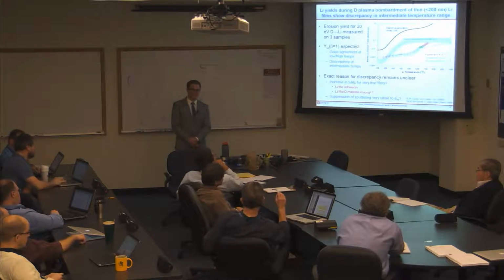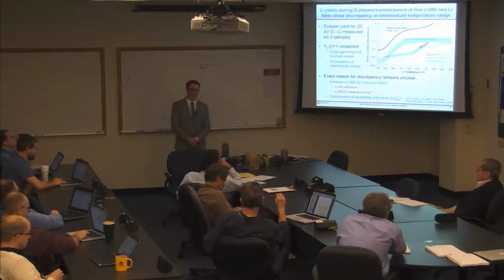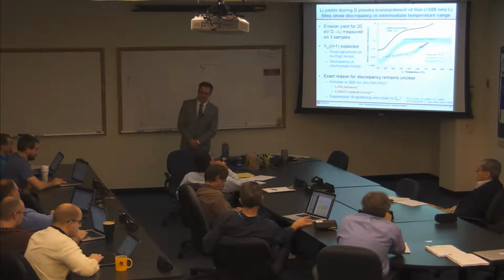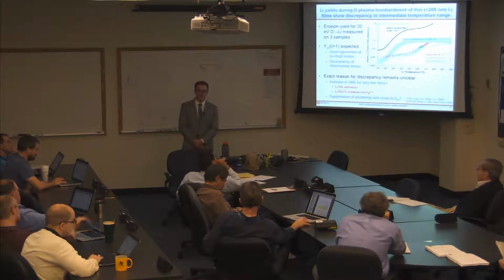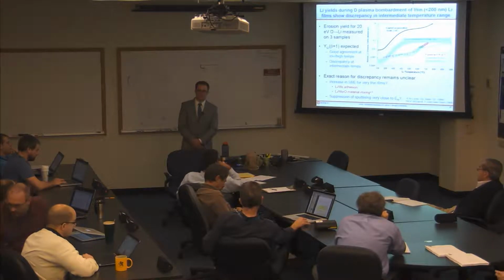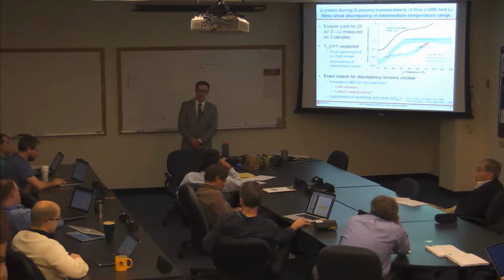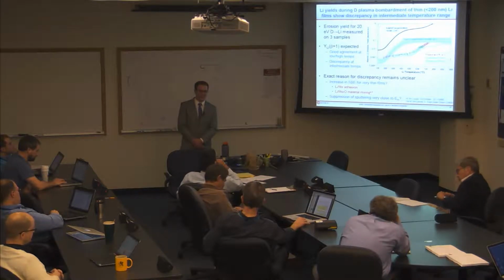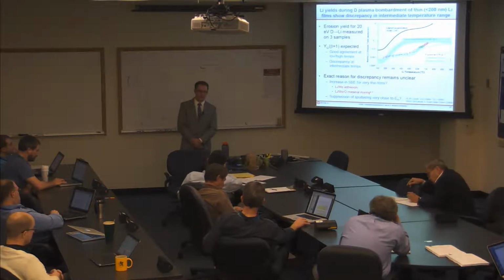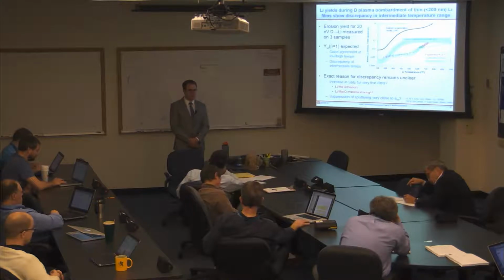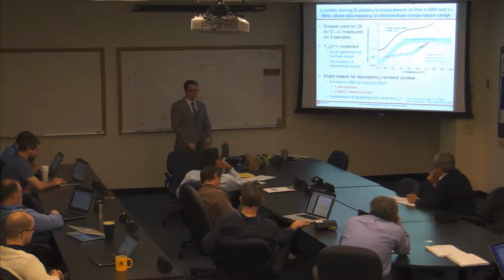Whatever is happening during the time evolution is going to affect the width of your layer, and it's going to compound on itself. So does your model just start at 600, or does it know that it came up through 300 and has been depositing? So you're saying, do I dynamically reduce the thickness as a function of time? Or do you suspect that happens in the experiment? The thickness is certainly dynamically reduced, but I'm assuming that it's uniform anyway. I'm assuming that you have complete saturation.